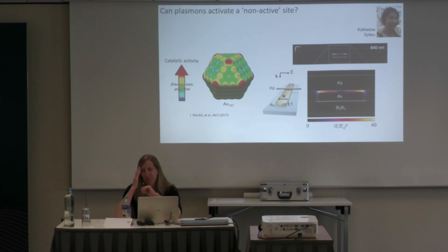Exactly. Okay. Yep. And the last question is, what is the role of the hot holes present in the system? Oh, that's a really great question. So we've thought mostly about hot electrons, but in certain systems like CO2 reduction, you'd probably wind up using a gold palladium system. And gold has interband transitions, and those can give rise to hot holes that are almost more important in driving catalysis than some of the hot carriers.